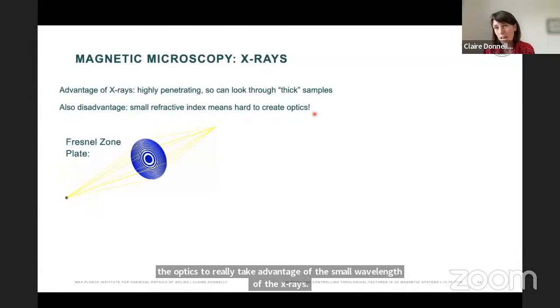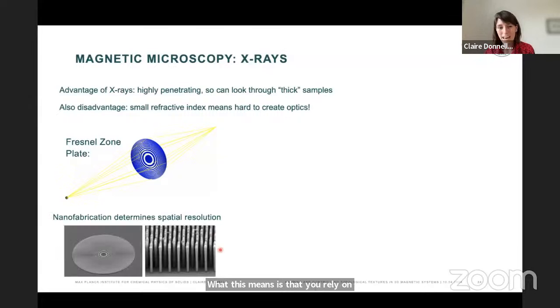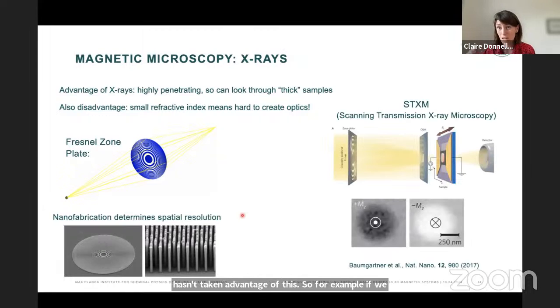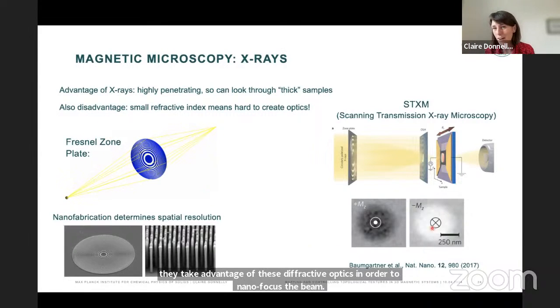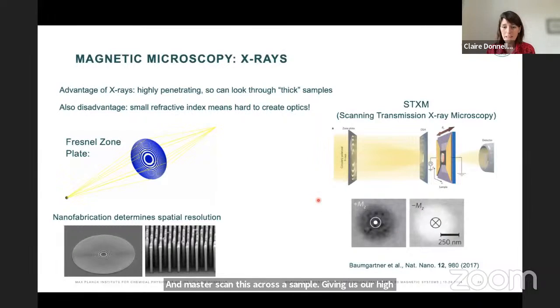What this means is that you rely on diffractive optics, which requires very high resolution nanopatterning. And traditionally, a lot of X-ray microscopy hasn't taken advantage of this. For example, scanning transmission X-ray microscopy takes advantage of these diffractive optics to nanofocus the beam and raster scan it across a sample, giving us our high spatial resolution images. But now the question is, what happens if we want to go beyond the limit of the lenses and actually go towards this wavelength-limited resolution for X-rays, which takes us down towards, or even potentially in the future below, the 1 nanometer level?